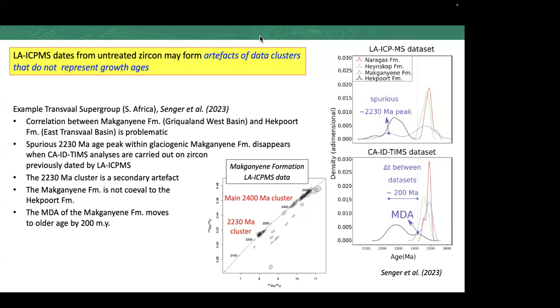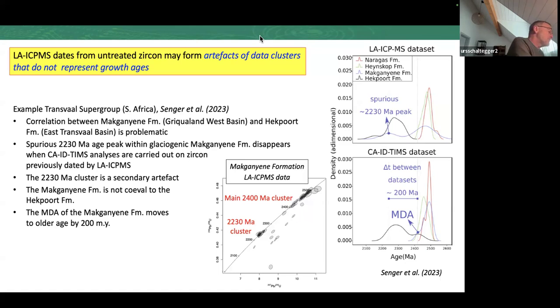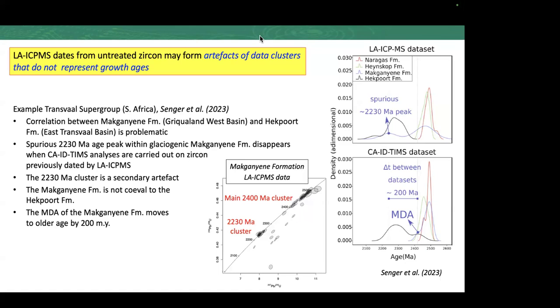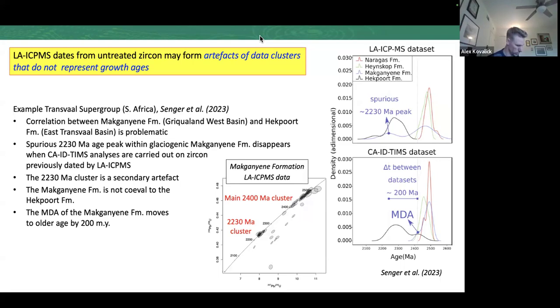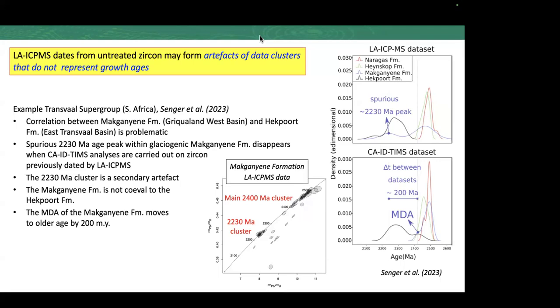The annealing is amazing. We do it now routinely, and I send a lot of zircons for pre-screening from ashes so that I can focus on the youngest grains, and it really improves the distribution of the data. Yeah. Another comment about chemical abrasion, as you said, it weakens the lattice. I did studies on the Makganyene problem actually, and I chemically abraded them. The 7-6 ages seemed fine, seemed agreeable, but all the data plotted above Concordia. So the matrix had been damaged in a way that we were getting uranium loss relative to the standards.